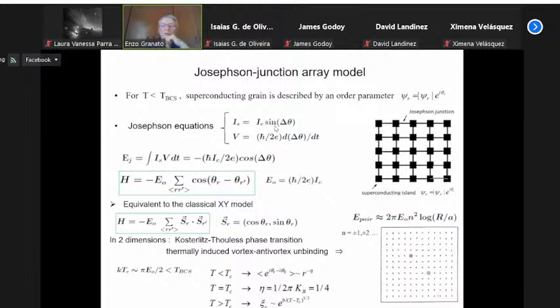In the original derivation of the Josephson relation, which leads to this equation here, the region between the grains was an insulator. But actually, this equation for the energy-phase relation is valid in more general situations, in which the region between the grains can be a metal or a superconductor with very weak superconductivity compared with the grains. And the grains don't have to be physical grains themselves. The whole thing could be a continuous superconductor, and the grains would mean local, larger regions with stronger superconductivity, and the weak links between the grains could be just a constriction in an otherwise uniform, homogeneous superconducting material.